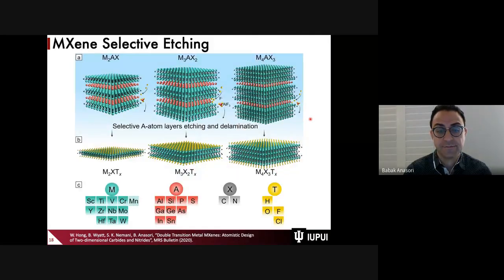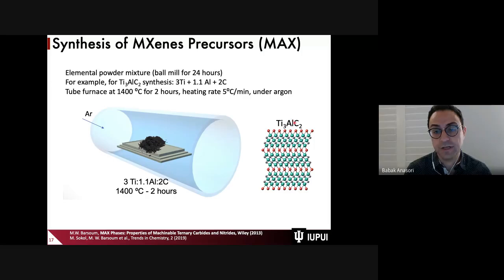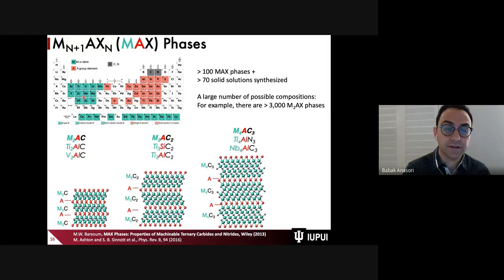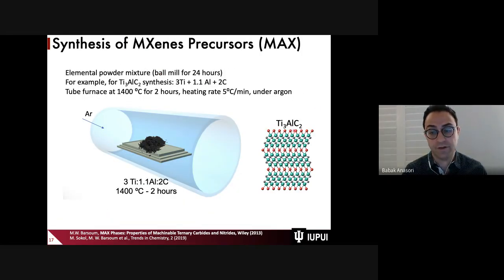After we make this material, we selectively remove the A layer that we added, for example, aluminum. Now, you might ask, why do we add aluminum if we want to remove it? Because if we do not add these A elements, using just transition metal and carbon or nitrogen, we will get the regular transition metal carbides, which are not layered, and we cannot make the two-dimensional nano-layered structure. So by introducing the aluminum, we make this layered structure as a precursor for layered two-dimensional MXenes.